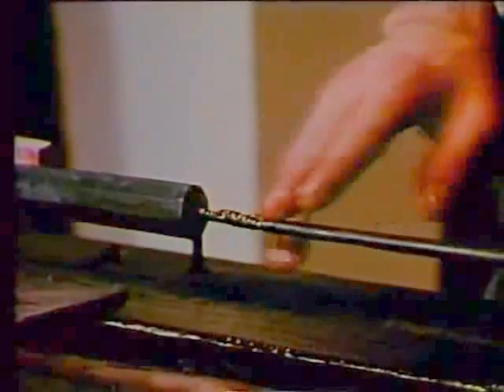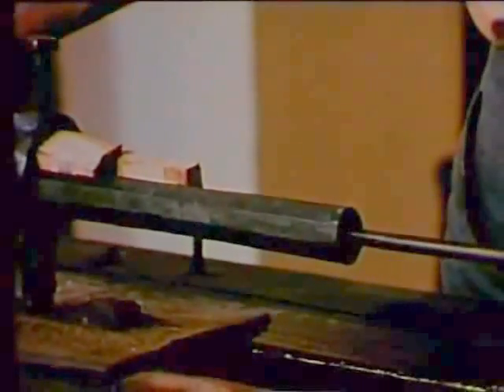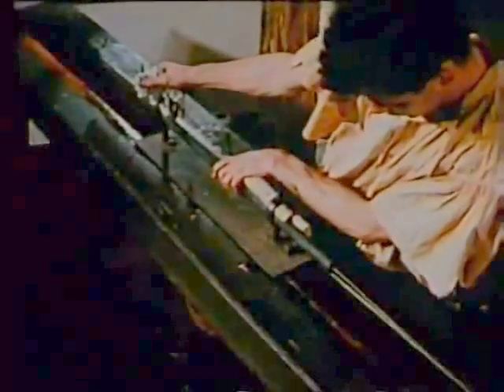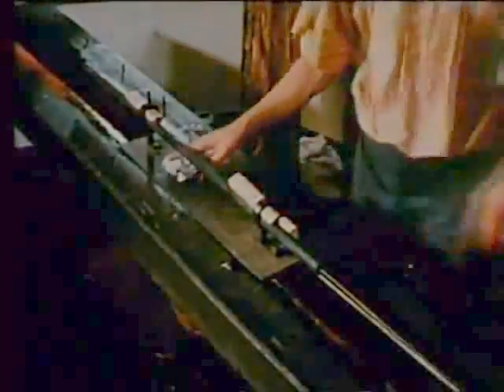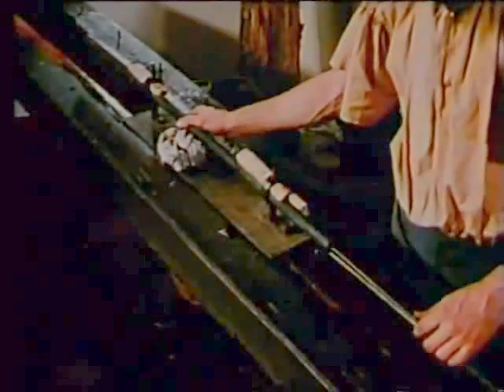Each new bit is a little larger in diameter and longer in cutting surface than the one before. We use about 12 to 15 rough bits. Once we get a bit cutting the whole length of the barrel, we drive it with the chain and weight. The gravity feed is ideal for this type of work because it will slow up at the hard spots. If the barrel advanced at a constant speed, it would break a lot of bits.